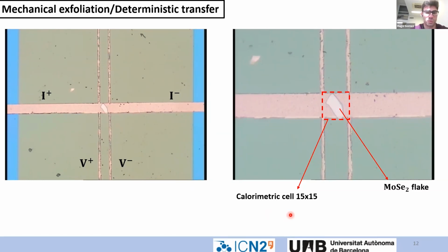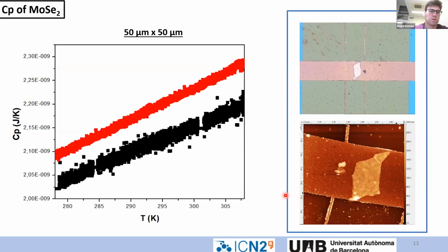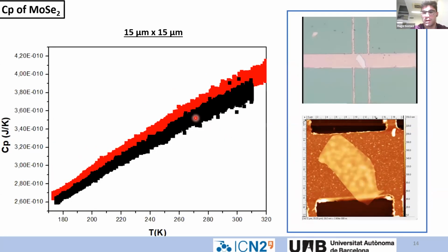We have calorimetric cells of different sizes: 15 by 15 micron and 50 by 50 micron. We select one or the other simply by taking into account the size of the flake that we want to study. Once we have done the transfer, we measure our calorimetric cell again, which is the red signal, and the signal we obtain is the sum of the calorimetric cell plus the molybdenum diselenide flake. We can do this again with the 50 by 50 micron cell. This is the AFM image of our chip, and with the 15 by 15 micron cell we get something really similar, with the transferred flake and its AFM image. You can see the signal of this transition metal chalcogenide is a little bit higher, of course.